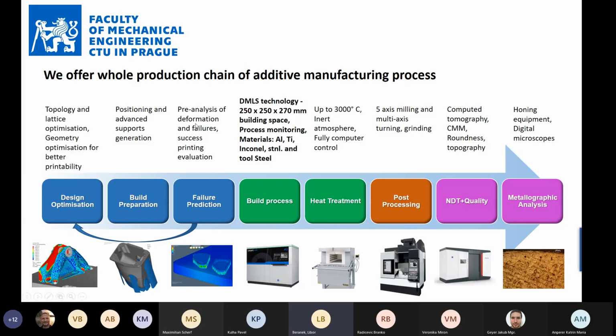Basically, we can analyze these deformations, potential failures, and collisions with the recoaters. Those are typical tasks that you simulate, and you can use these results to change the geometry you want to print, basically trying to invert the deformations within the geometry. And then of course you have to prepare the build regarding the positioning of the part, generating supports and so on.